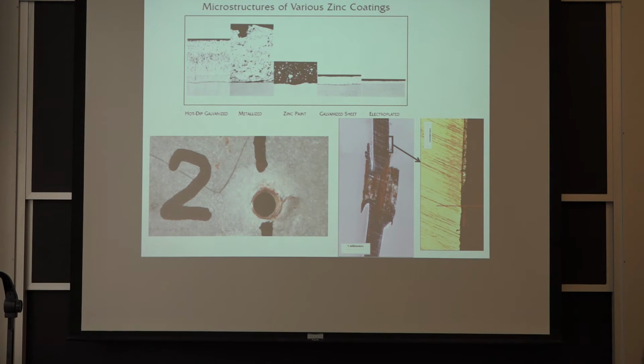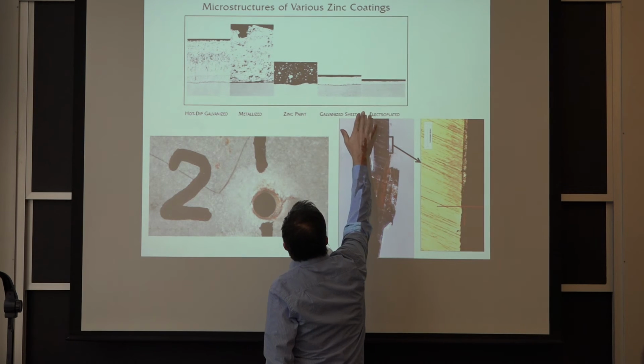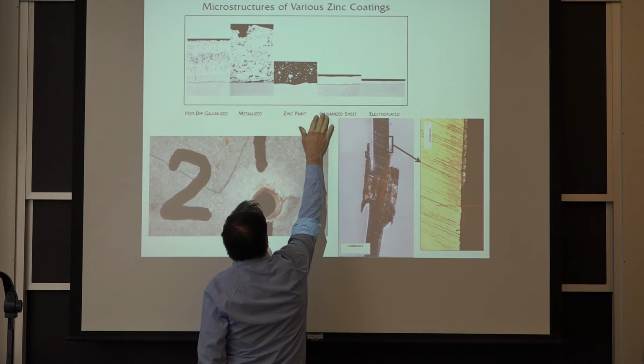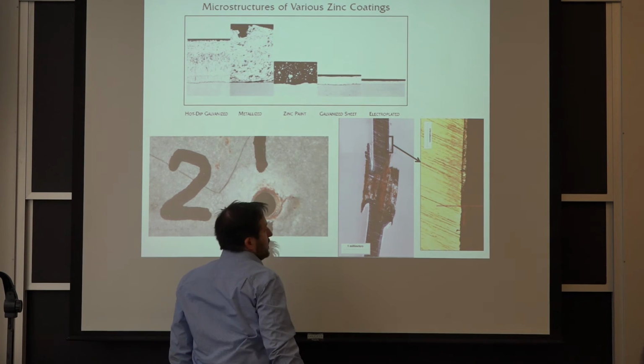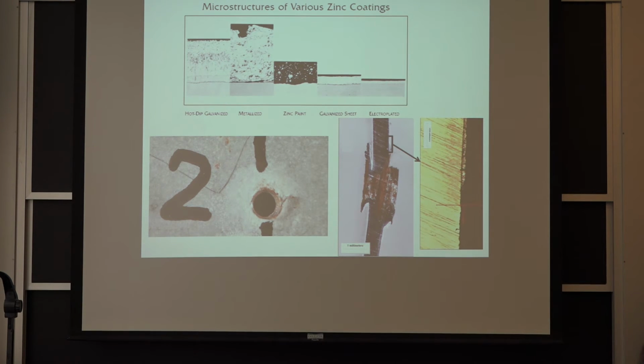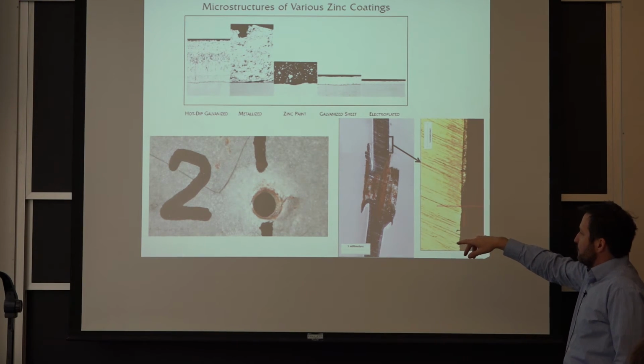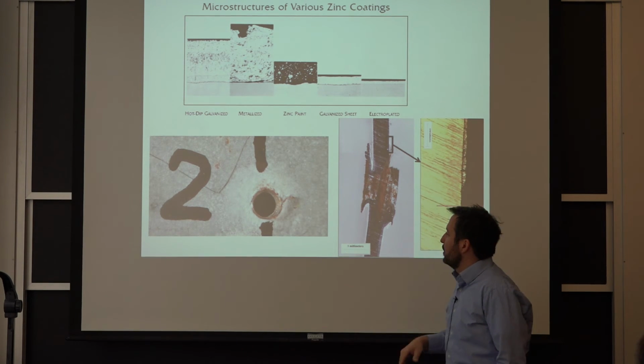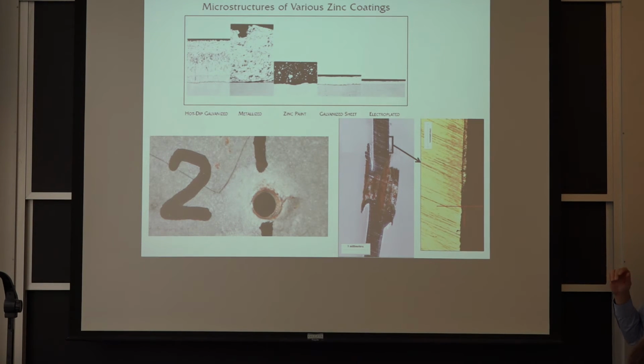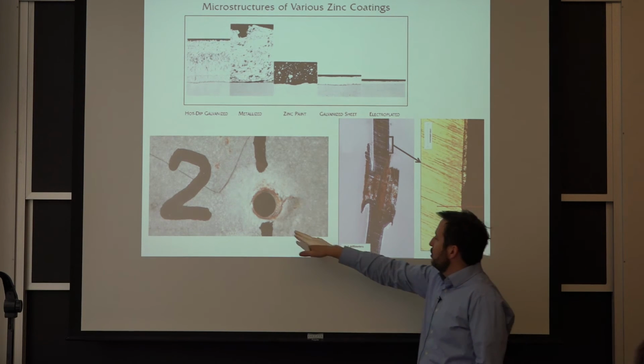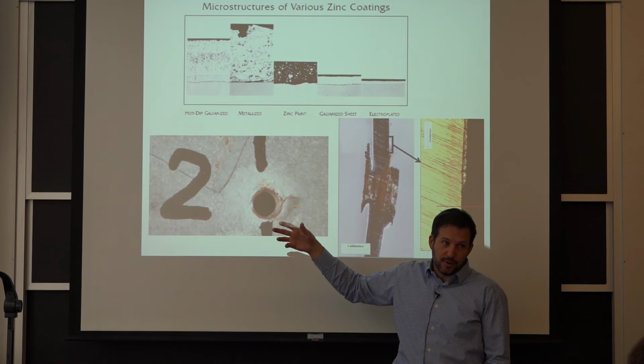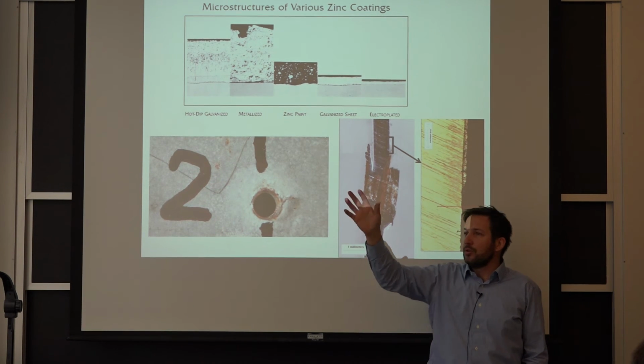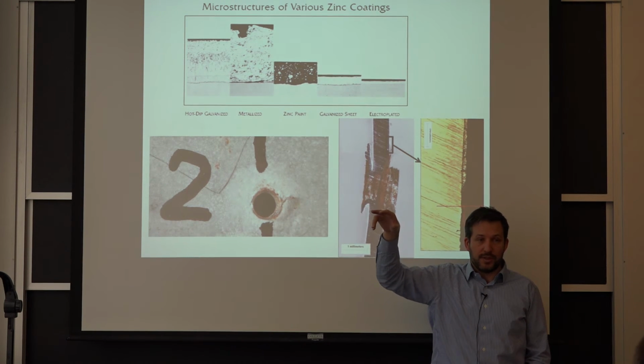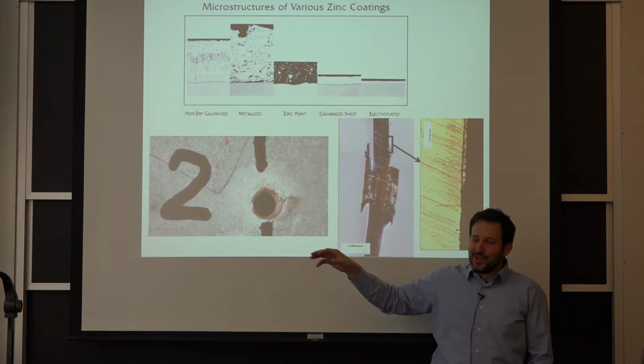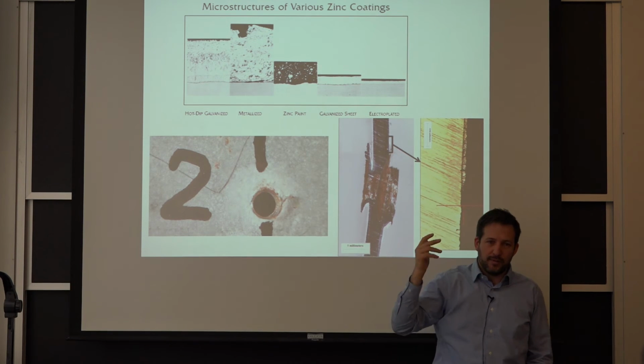There's, of course, a difference in the service life of having these cheap fasteners, the galvanizing that you have on the body of a car, and then the hot dip galvanized or sprayed on zinc that is a lot thicker. It becomes important in a lot of applications. This is an example of just a screw showing that when you drill the hole, you expose the galvanizing, and that itself leads to some corrosion. The idea is to control that corrosion, so you can use the zinc to protect that hole from growing. This is real trouble if it's the structural steel to hold the entire cladding for the building. So we have that on a building, for example, different layers, and then there's one piece holding the other. So if you lose metal around that hole, you lose the thread, everything falls off, no good.